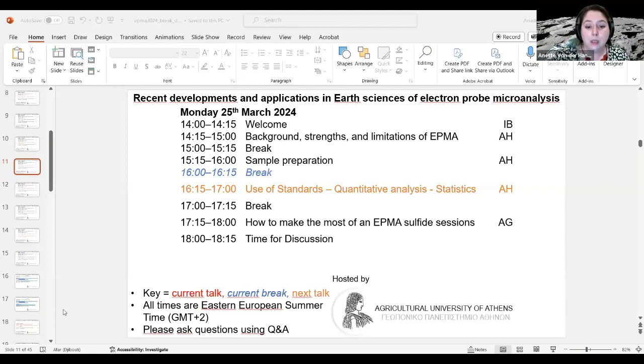Certain software, like the Probe software, can now correct for sample tilt. So again, it's not always possible to avoid it, but we're getting better and better at dealing with the data and potentially correcting it. But that doesn't mean that we can just ignore that and let the software do it. It will make a significant contribution to facilitating or correcting data after the fact where a thin section wasn't correctly slid into the holder.